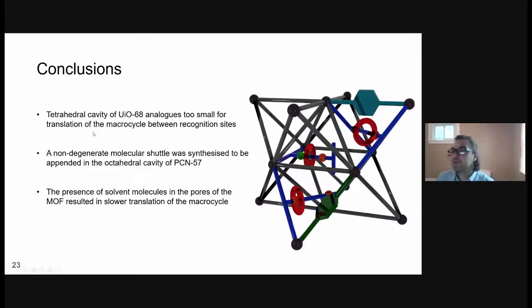So just to summarize what I've covered in this presentation, with these UiO-68 derivatives, we can cross-link the tetrahedral cavity with degenerate molecular shuttle-based ligands. However, while we can control the position of the macrocycle based on the nature of the co-ligand, we don't get any motion between the two recognition sites. However, if we instead append a non-degenerate molecular shuttle into the octahedral cavity, we can get translational motion, which is dependent on whether the MOF is activated or solvated.